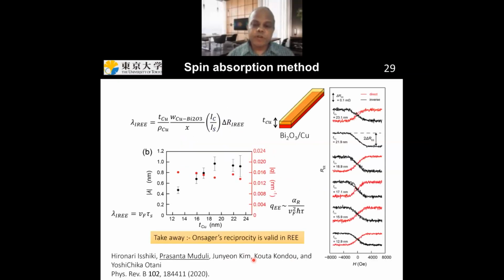To confirm this, we also made multiple reproducibility checks in which we fabricated devices where we varied the thickness of the copper from 12.9 nanometers up to 23.1 nanometers. In all the devices, we found that the signals due to the Rashba-Edelstein effect and the inverse Rashba-Edelstein effect have equal magnitude. We also calculated the Rashba-Edelstein length and the q, and found that they don't depend on the thickness of the copper. This confirms that the spin charge conversion is not a bulk effect; it is most likely an interface effect. So the main takeaway from this study is that Onsager's reciprocity is valid in the case of the Rashba-Edelstein effect, similar to the spin Hall effect.